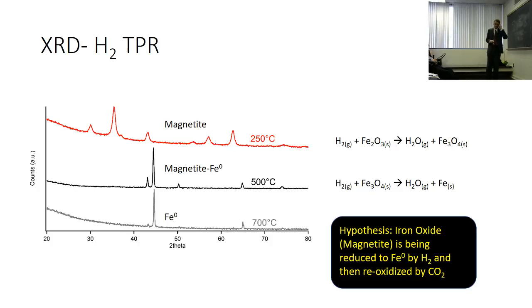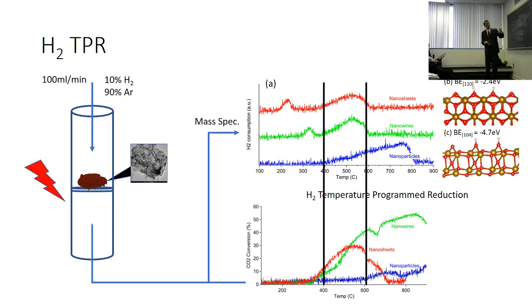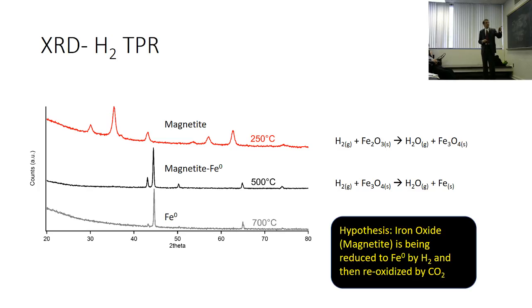magnetite. Magnetite is a reduced form of hematite, and what you find is I took the nanosheets out at different temperatures: 250 C, 500 C, 700 C, to see what was going on. What you find is magnetite emerges at 250 C. If we go back, the peak is at 225, so right after that peak, now your material is magnetite.